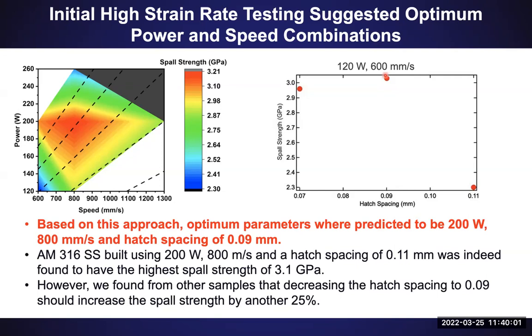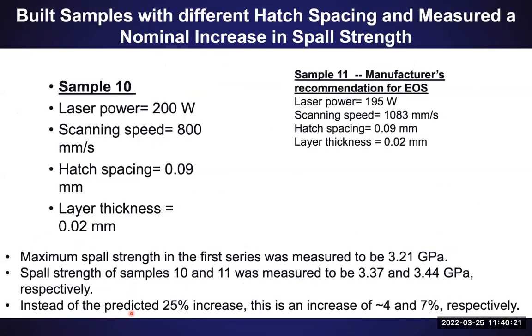However, we did not have that sample. We had a sample with a hatch spacing of about 0.11, which had a Spall strength of 3.1 GPa. And we thought, okay, if we can optimize the hatch spacing, we might be able to increase the Spall strength of the material. If we increase the stress required for void nucleation, we've basically made a material better for applications under extreme conditions.